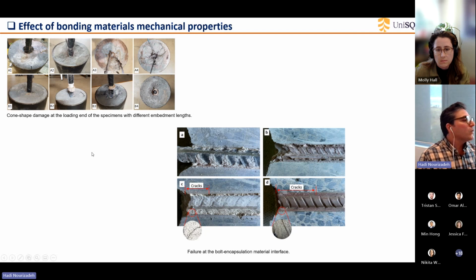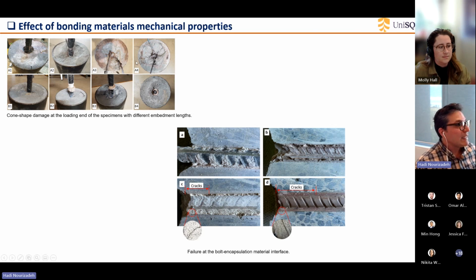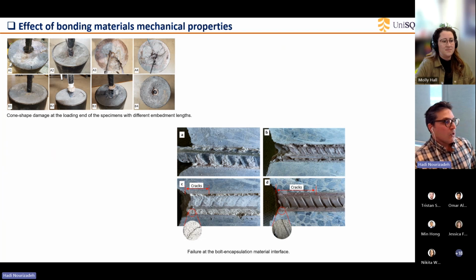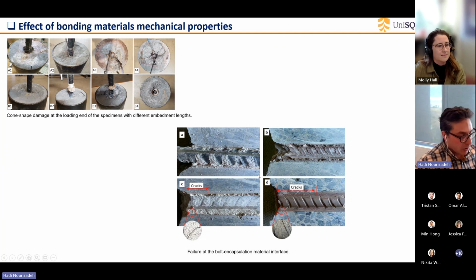We also analyzed the failure modes of these samples. We realized that for the materials with higher mechanical property, rather than having radial cracks, we see some cone-shaped failure on the surrounding rock. This is mostly important in civil engineering rather than mining. We also sliced our samples, and we could correlate the type of the bonding agent with the cracks and the failure modes of the bolt-grout interface.